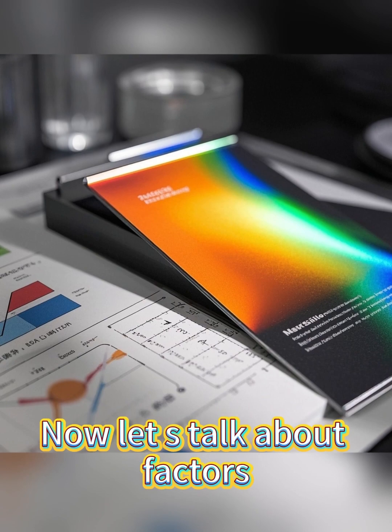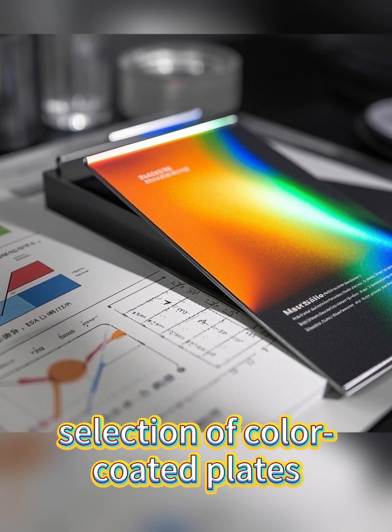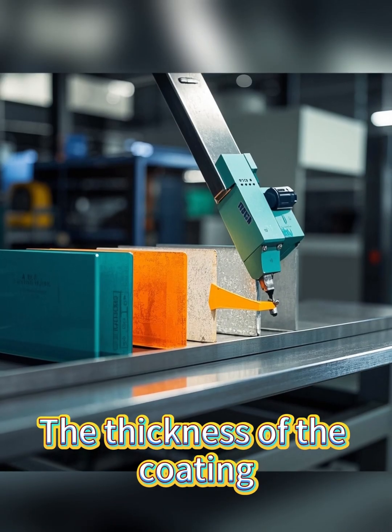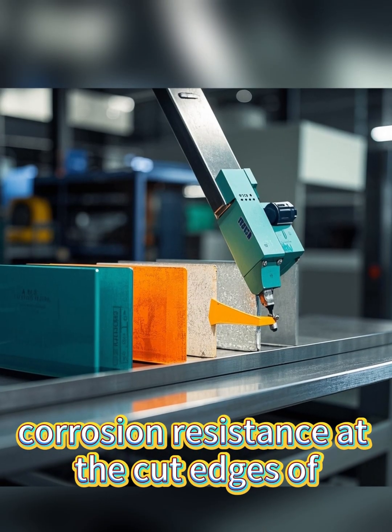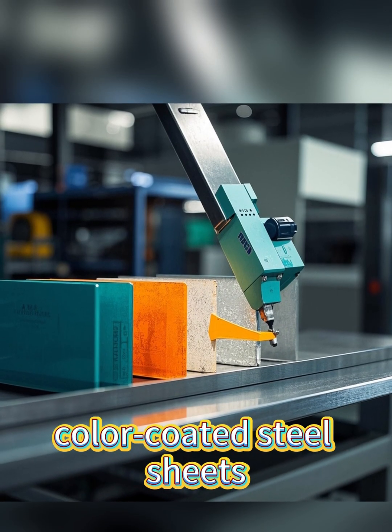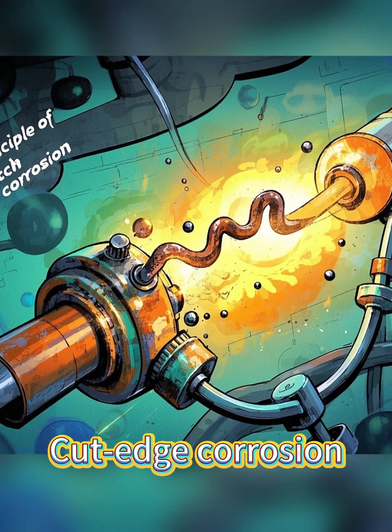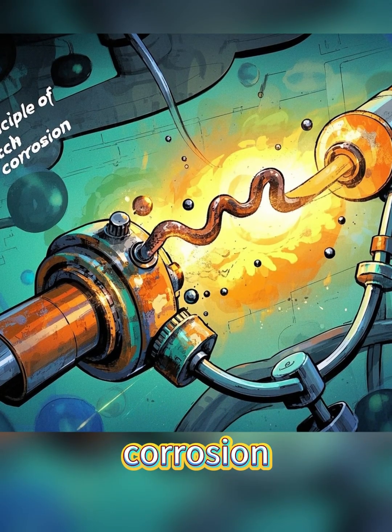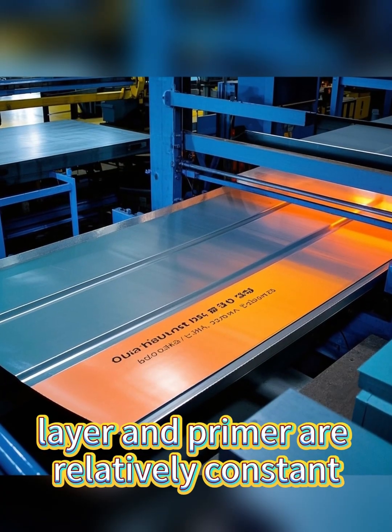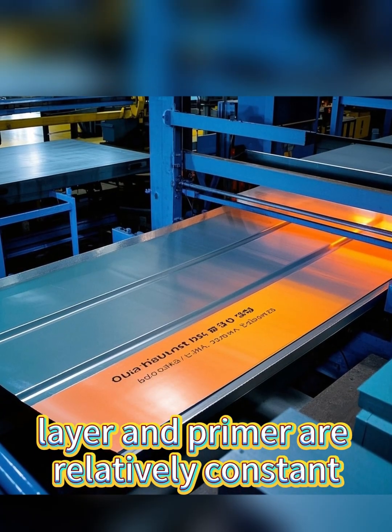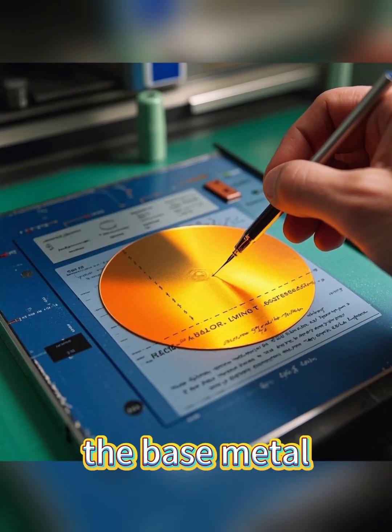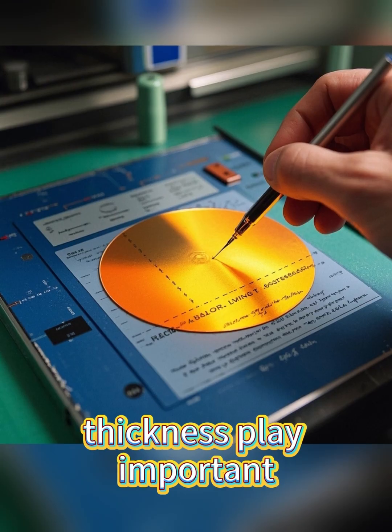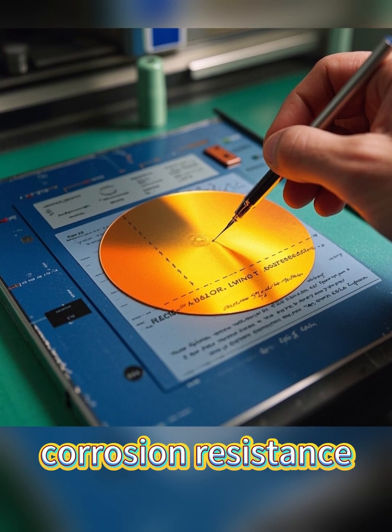Now, let's talk about factors influencing the thickness selection of color-coded plates. The thickness of the coating significantly affects the corrosion resistance at the cut edges of color-coded steel sheets. Cut-edge corrosion is a type of electrochemical corrosion. While the pre-treatment layer and primer are relatively constant under normal conditions, the base metal thickness and coating thickness play important roles in cut-edge corrosion resistance.